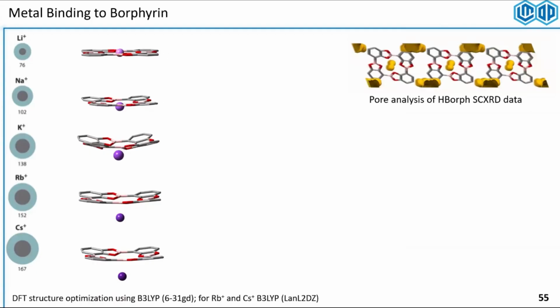The next question was, what can we do with it? So I started looking at some basic density functional theory calculations, just put a metal ion inside and let the system relax and see what happens. We found that only lithium stays inside. As soon as we change into sodium or anything bigger, the macrocycle has to bend to still have a maximum interaction. And this bending, even though it may occur in the gas phase, in solution it looks almost impossible because you have to bend these boronic acids and phenyl rings and twist them out of plane.